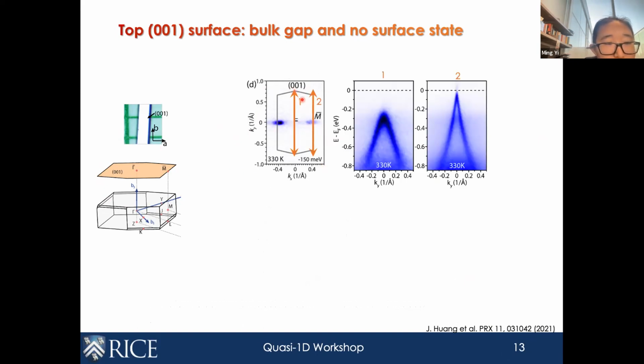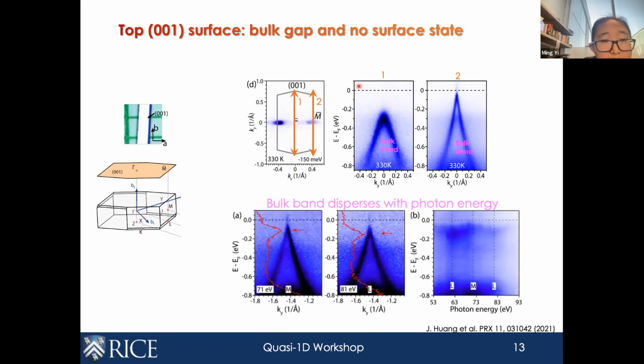If we take two cuts, you can see that they both show hole-like bands with the band top. And at the gamma point, there's a large gap. And then on the side of the Brillouin zone, we have a much smaller gap. What are these states? Well, we can vary the photon energy to probe the kz dimension of these bands. And from that kz dependence, we can focus around here and vary the photon energy. We can see the band top here actually varies periodically with photon energy. That will indicate that this is a bulk band because surface states won't disperse along kz. So we know that these two hole bands are bulk bands.